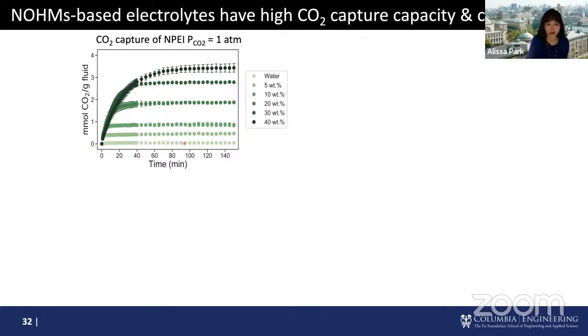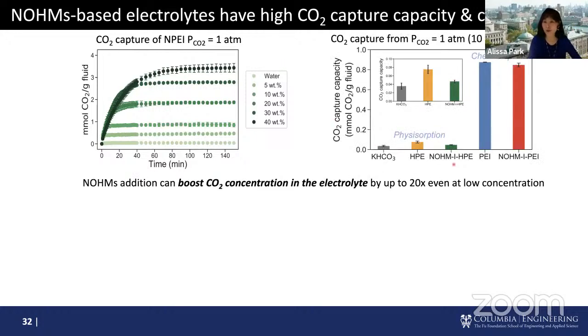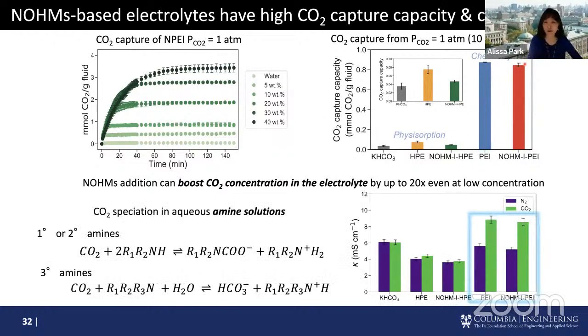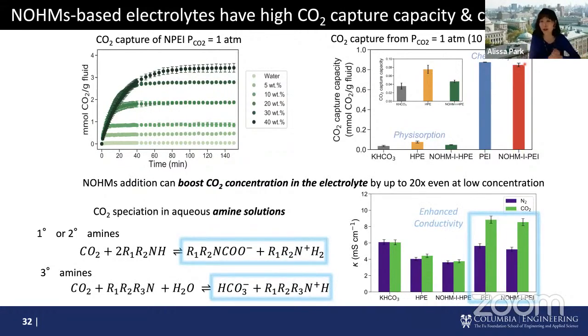As I mentioned, this is the water system, just conventional electrolyte, with very low solubility of CO2. As we increase the NOHMs loading, a lot more CO2 can be captured and loaded onto this NOHMs-based electrolyte. And that really depends on physisorption versus chemisorption. Of course, chemisorption is a lot higher than physisorption. Conductivity also gets impacted if you do chemisorption, because we are now making a lot of ionic species, so we actually enhance the conductivity of the overall system.